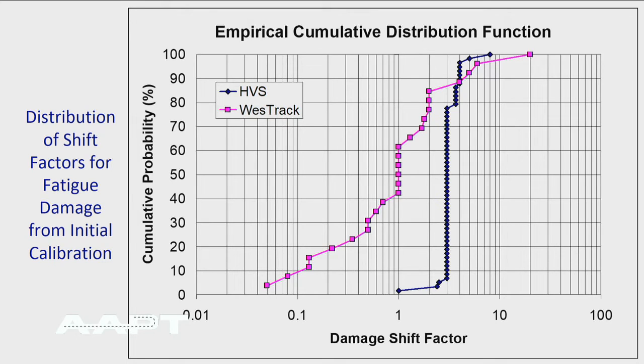These were our calibration factors from the HVS test sections and from WestTrack. And this is for the damage. And you can see a range of shift factors. So what we're using in the software right now is the average shift factor across those.